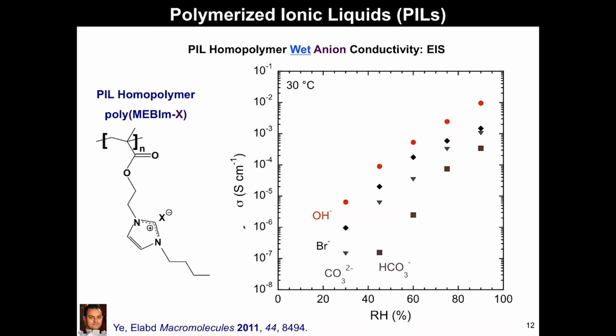So here you can see the conductivity as a function of the relative humidity, and as you increase the relative humidity, you'll see the ion mobility will increase by decades. And this is just a completely different ion transport mechanism, pretty similar to those you may be familiar with, things like Nafion or sulfonated polymers that have proton conductivity. This is very much a water-assisted process, not so much dictated by the segmental motion of the polymer chains.